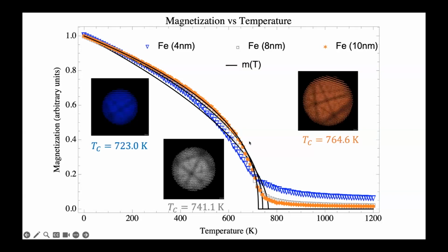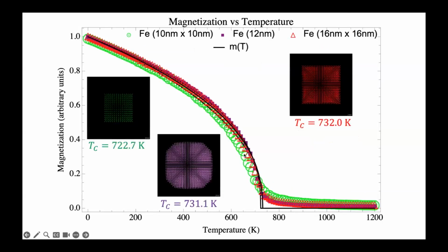Now we change the shape of the nanoparticles. Plasmonic nanoparticles usually depend on shape and size. When you change the magnetic nanoparticle into a block or an octagon, we know that most plasmonics depend on the shape; if it has a lot of sharp edges or corners, light gets scattered in different places. But here, changing the shape doesn't really have any effect; the Curie temperature is most likely the same, even when we change the shape of the nanoparticle.